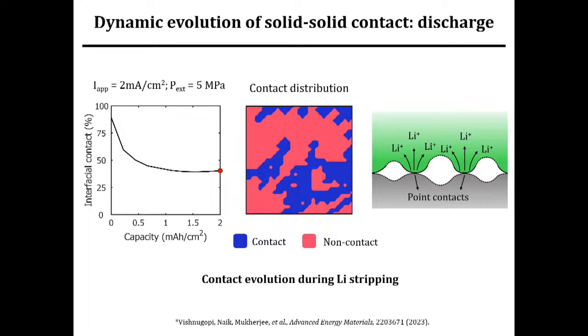We see here a video of how the metal interface dynamically evolves, and the red spots show the occurrence of voids or physical gaps at the solid-solid interface. These are highly non-desirable because they result in reaction hotspots, and in a subsequent plating cycle, there can be preferential spots at which lithium nucleates and penetrates into the solid electrolyte separator.